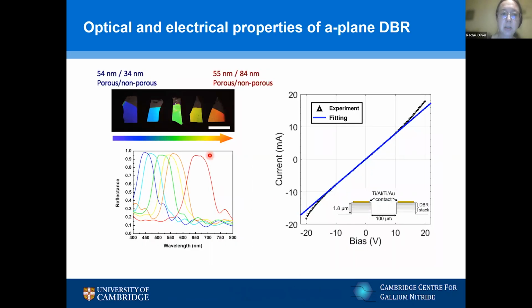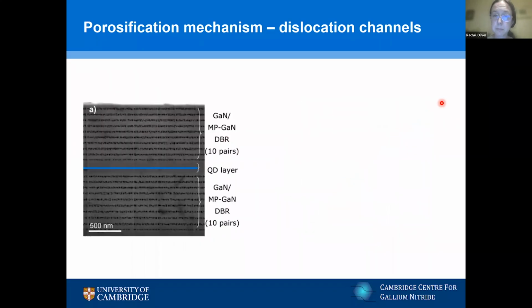And by changing the layer thicknesses in our porous structures, we can tune the wavelength of the reflectance, get very nice high reflectances from usually sort of 10 layer, 8 layer structures because of this large refractive index contrast, but at any wavelength we happen to design for. The material here is also conducting, although not as conducting as before porosification.